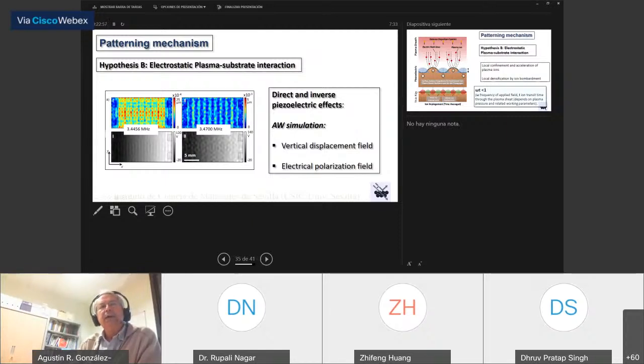So actually, when we activate a piezoelectric substrate, these are simulations. We get the changes in the amplitudes, as we have already seen experimentally, but also we are producing a change in the electrical polarization, a difference in electrical polarization, which is illustrated in this map here at the bottom, where the difference in electrical potential between, for example, this gray area and this white area is in the order of 10, 12, 14 volts, which means that locally the polarization degree of the surface is completely different in areas which differ, at the frequency which we are using, by a distance in the order of 0.51 millimeter.